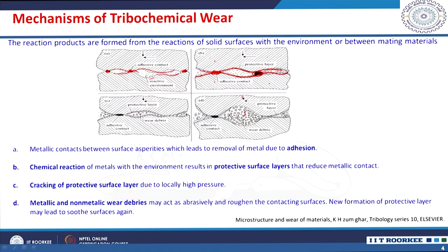The metallic or non-metallic wear debris may act as abrasive particles and roughen the contacting surfaces. The new formation of a protective layer may again smoothen the surface. So, it is a continuous process of first making an asperity-asperity contact, giving rise to adhesion, and then, because of the reaction with the environment, these metallic surfaces will have protective layers. But as the pressure is increased at the contacts, the layers are broken and the wear is removed as debris. Then again there is a protective layer. So, it is a continuous formation and removal of the layer, and they actually contribute to the tribochemical wear.